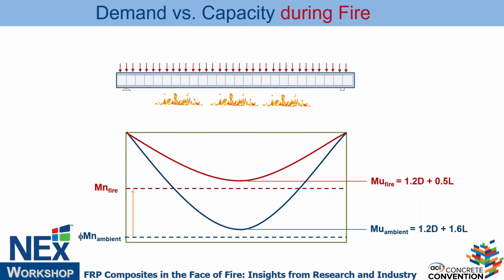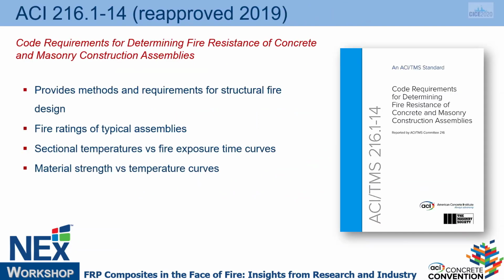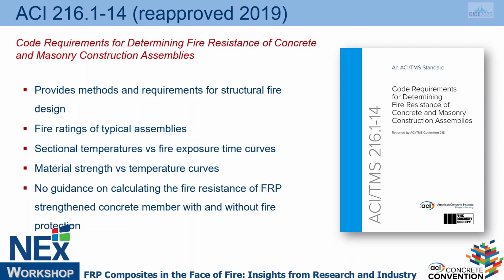But it doesn't happen all the time. If this drops, then I don't have adequate fire rating. Okay, how do I figure that out now? To do this, I need to determine the temperature of the steel so I can figure out the strength of the steel, so I can plug into my shear or flexure capacity calculation and figure out the capacity. Well, we have data available in ACI 216 that can help us with this. It gives us the relationship between temperature and strength, and the temperature profile within the cross section.